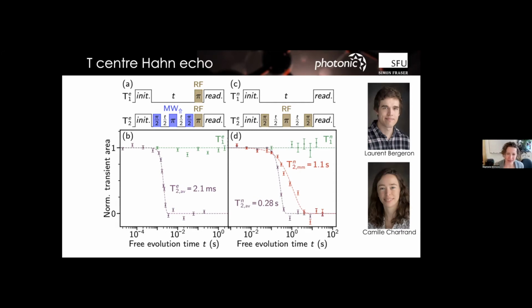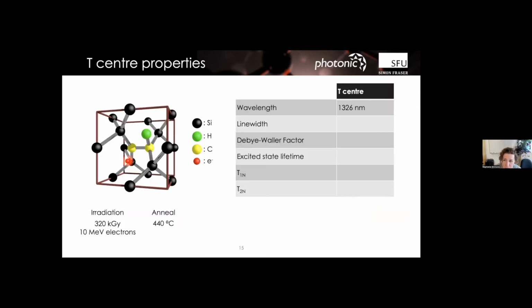We stopped. The T1 times are just like any other spin in silicon at low temperatures, longer than you care to measure. For phosphorus at these temperatures and fields, it's like weeks. So T1 is never really the thing to push on. T2 is usually a magnet phase stability issue, and dynamic decoupling gets you most of the way there, but we just decided to get on with it. So yeah, these are Hahn echo numbers for the electron and the hydrogen. So this is going to be another break point when I ask for questions. This was a lot of bulk spectroscopy work. The next phase of the talk is going to be about integration and scaling of these things.